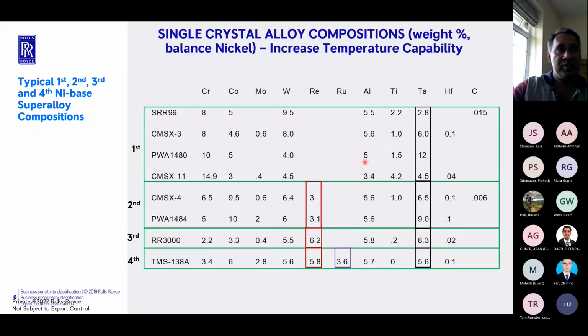When you go from the first generation alloys to second generation alloys, and that typically happened in the early 90s, the big difference between first and second generation is the addition of rhenium. Rhenium is one of the main elements added to second generation alloys. Again, the reason for adding rhenium is you want to make it even stronger than the first generation alloy. So the main reason for going from 1 to 2 is to increase the strength. And one of the ways you can increase the strength is by the addition of rhenium.